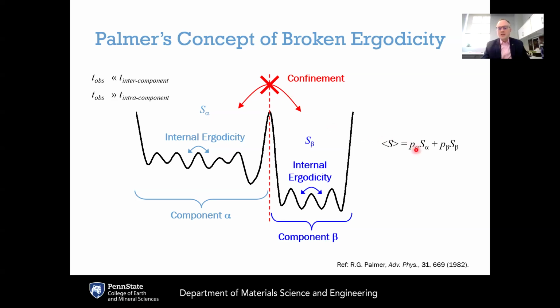And because of this assumption of internal ergodicity and the assumption of confinement, any thermodynamic property, such as entropy, can be described as just a weighted summation over the properties that correspond to the individual components. So, for example, if you have an entropy of the system, if it happens to be confined in component alpha, it would have an entropy S alpha based on the number of microstates within component alpha. And then there's a probability of the system being confined in component alpha that is P alpha.